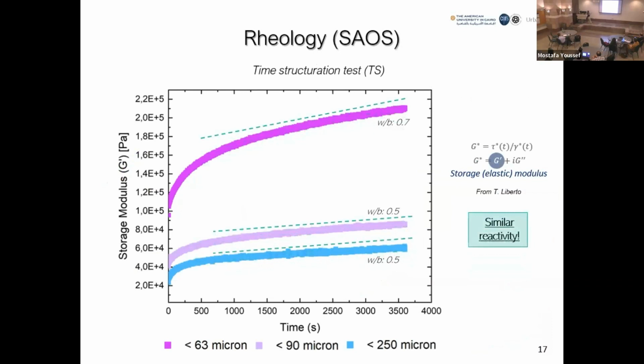And as you can see, the fuchsia curve presents a slope a little bit higher with respect to the other two, because in this case it represents the more reactive part, I mean, the real binder, less than 63 micron. But if you take an overall view of all of these three lines, the difference is not so big. And so for this reason, I was able to collect all the powder that was able to pass at 250 micron, but without losing the reactivity of the powder.